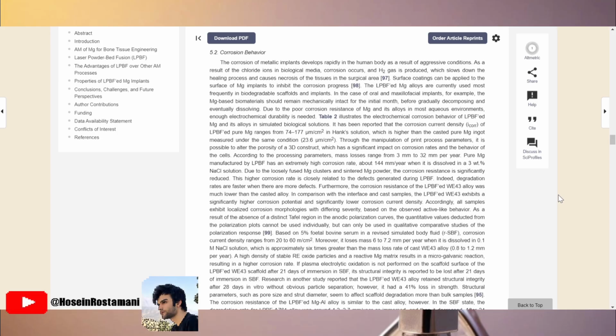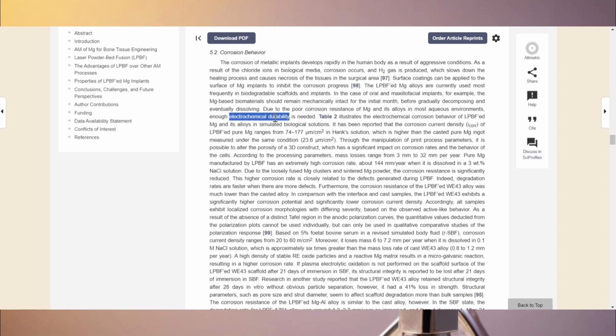Surface coatings are commonly used to slow corrosion in magnesium implants, particularly magnesium implants used in biomedical applications as biodegradable implants, for example in oral or maxillofacial applications. These materials need to maintain their mechanical integrity initially before gradually degrading and dissolving. Given the poor corrosion resistance of magnesium and its alloys in aqueous environments, achieving sufficient electrochemical durability is crucial. As you notice, the corrosion behavior of LPBF fabricated magnesium alloys varies depending on composition and processing parameters. Corrosion rates are typically higher than cast alloys, primarily due to defects such as porosity and incomplete fusion.